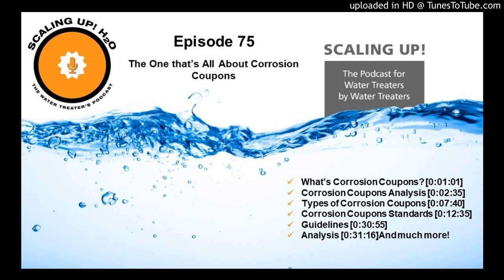Now, it's very specific in how we do that because we don't want to remove more metal than we have to. We just want to get the byproducts off. Once we get it to that stage, we then dry them. I set them all out flat on our bench, and then we have to use the envelopes that you gave us to identify the serial number to the coupon, and then we start weighing each coupon again down to the 10,000th of a gram. That's very, very specific. And of course, that's not your ordinary scale. These are special metallurgical scales.